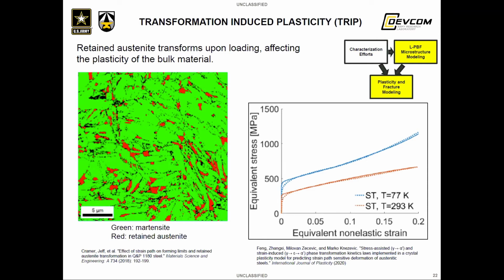To incorporate the effects of transformation-induced plasticity, we are working with one of our academic partners at UNH to develop a crystal plasticity code for use with AF9628 that was previously applied to stainless steels. You could call AF9628 a TRIP-assisted steel because it has some small portion of the material that is retained as austenite, whereas an austenitic stainless steel, for example, would be a full TRIP steel. On the left, I've shown an example phase map for a different steel, but it's a TRIP-assisted steel with a similar proportion of retained austenite. On the right are some of the experimentally measured and simulated plastic responses of an austenitic stainless steel using the model developed at UNH. The hardening behavior in this material is very heavily influenced by the formation of martensite as the deformation causes austenite to transform. And we suspect that AF9628 will be similarly affected by the transformation of its retained austenite.